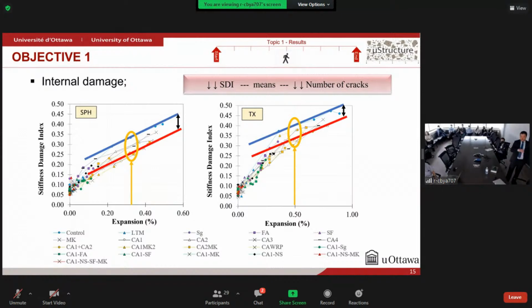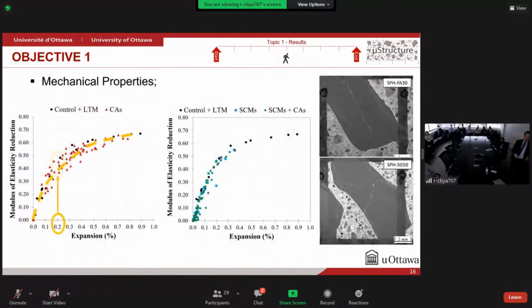So to try to understand this behavior, we then test the specimens for a mechanical property that is aggregate dependent. And as we can see, for comparable expansion amplitudes, it doesn't matter which concrete mixture we are using. If we are using crystalline admixtures, SCMs, doesn't matter. The modulus of elasticity loss is the same for all concrete mixtures for comparable expansion amplitudes.